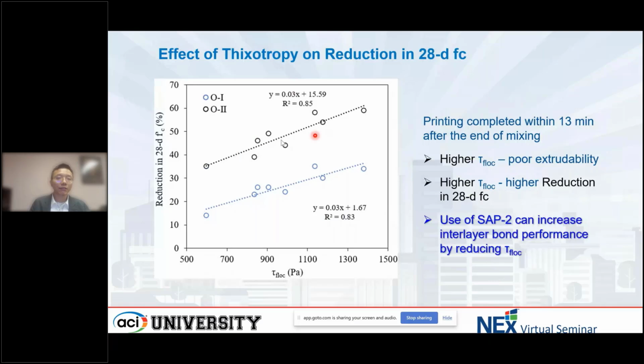This figure shows the relation of flocculation on the reduction in 28-day compressive strength. As I mentioned earlier, SAP2 reduces the floc value, and SAP1 increases the floc value. We found that there is a strong relationship between the floc value and the reduction in 28-day compressive strength. That's why SAP2 can improve the compressive strength. It reduces the floc, improves the surface quality, and improves the bond strength.